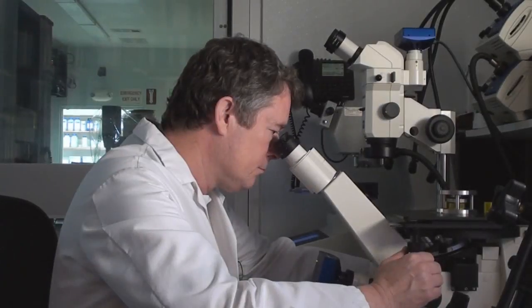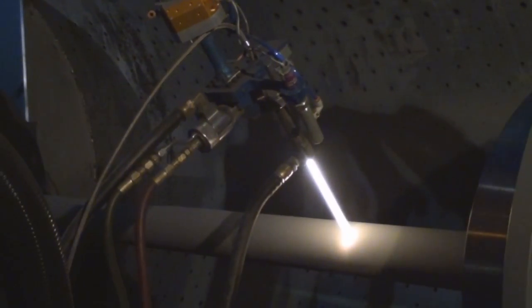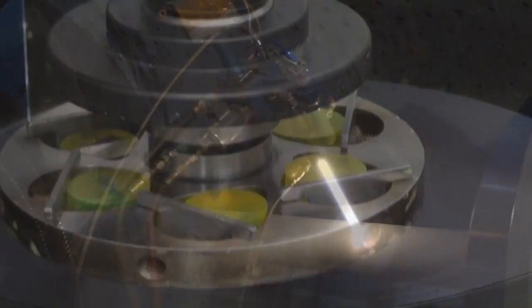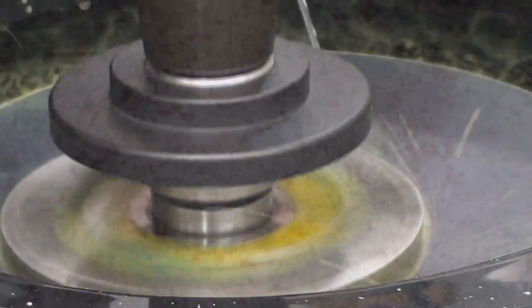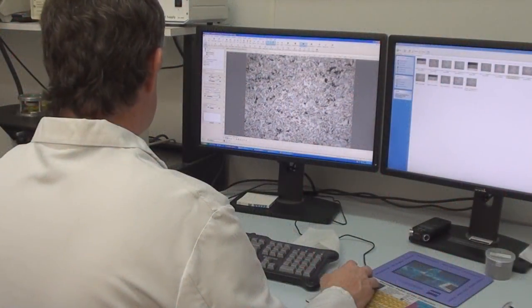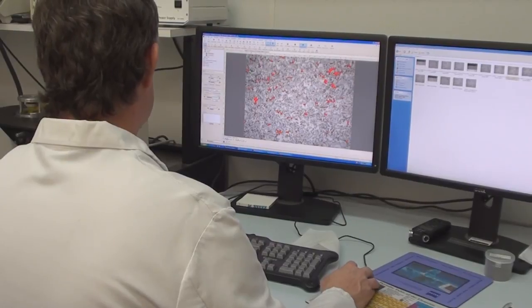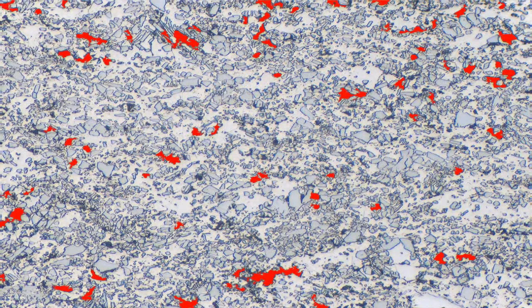Porosity is a key factor in thermal spray coating quality because a less porous, denser coating will be tougher and will generally form a better seal. Following metallographic preparation, we measure the area percent porosity of thermal spray coatings using a software program that detects porous regions and colorizes them red with 250 nanometer accuracy. Higher than specified porosity can cause a reduction in the cohesive bonding strength and Vickers hardness, reducing the coating's overall toughness and wear resistance.